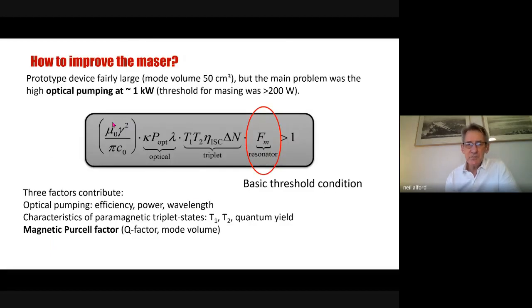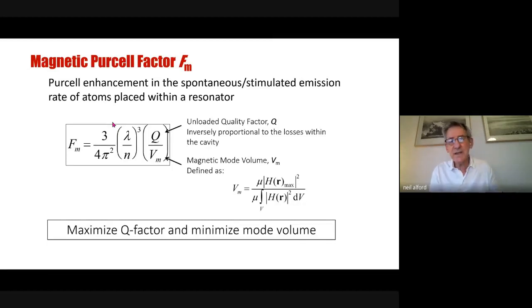So how can we improve the maser? Well, there are three factors that contribute. Optical pumping, the efficiency, the power and the wavelength; the characteristics of the triplet states, and that's the quantum yield; and most importantly for us, the magnetic Purcell factor, which I'll just talk about now. So this was the key to miniaturizing the maser itself. And what you can see here is that really the Purcell factor is the quality factor of the resonator divided by the magnetic mode volume. And so what we want to do is to maximize the Q factor and to minimize the mode volume itself.